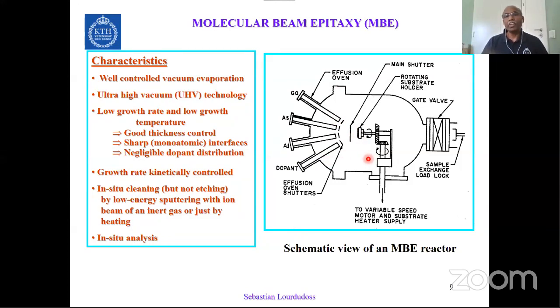And that is why only the reaction at the substrate is the one which is dependent. That is why it is called a kinetically controlled process. So again, here you can control the growth rate at the monolayer level. And that is why this is also used for very advanced device fabrication.